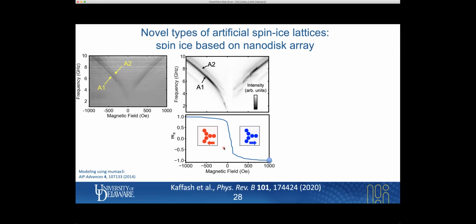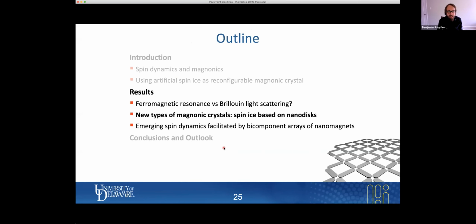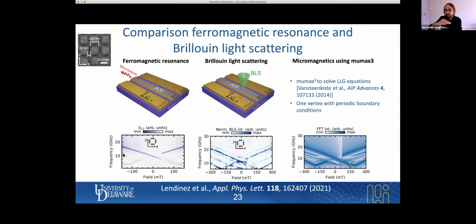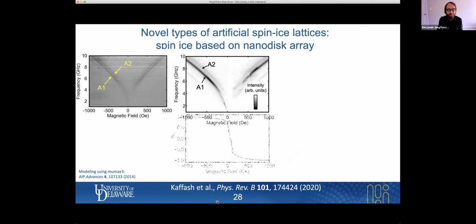Yes, please. So about this mode splitting, is it because you have a degree of freedom and you can have clockwise and anti-clockwise rotation of these, or what's the origin of this splitting? The origin is just that it couples, so you can get some modes which, if you rotate the angle, some of these go down, they become very flat, and eventually these modes here go up, and they merge and they cross. It could be interpreted almost like a hybridization of the modes. And because they are different types of the lattice, they are at the same frequency. Okay, got it. Thank you. So that was really quick what we observed there.